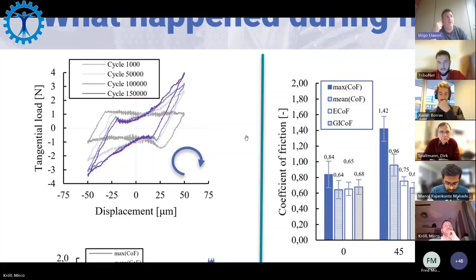Then the next one is the energy coefficient of friction, which in essence you have to calculate the dissipated energy, the area in that graph, and then you divide by the normal force, and here it is the key, the slip distance. Okay, the applied displacement and the slip distance are not the same, because of the compliance of the contact system. So in the case that you have a really large compliance, then the values of the energy coefficient of friction can change a lot. So that's the third one.